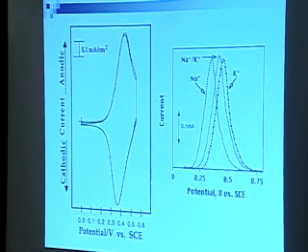There it is. Turns out that you don't get two waves, like I'm showing you there. When you have mixtures of sodium and potassium, you get one wave. It's not like the sodium cesium. You get one wave that marches all the way from the pure sodium case to the pure cesium case as you change that ratio. So you can use it analytically, but it doesn't do the same thing. It doesn't give you the two waves, even though there's enough potential spread there that you should be able to see both the waves.